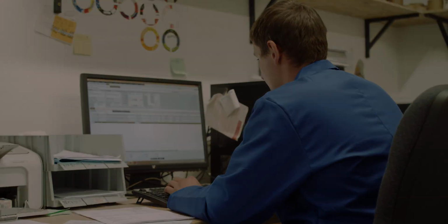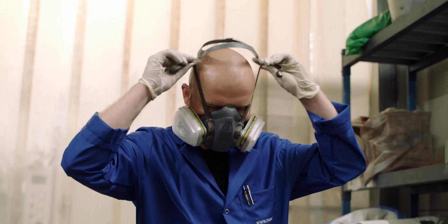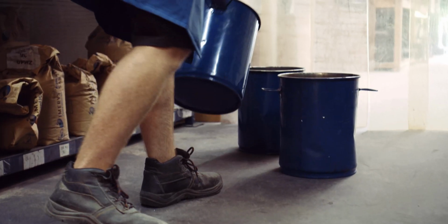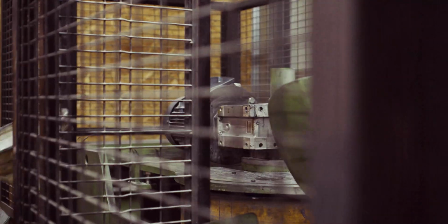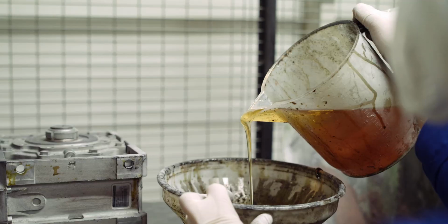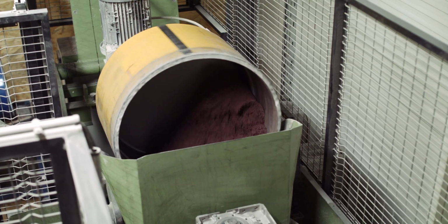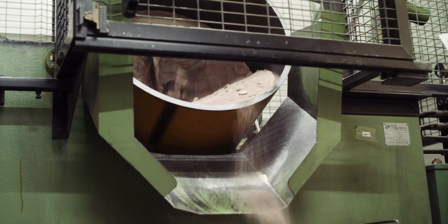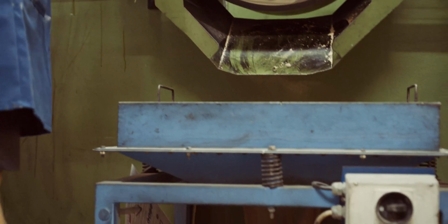conditions and opportunities. After careful preparation of the process documentation for the ordered product, the mixing process follows, where, depending on the product type, the appropriate abrasive grains are selected and first wetted with liquid resin, and in the next phase, powder fillers and powder resin are added. This produces a consistent blend for the production of cutting and grinding discs or resin-bound grinders.